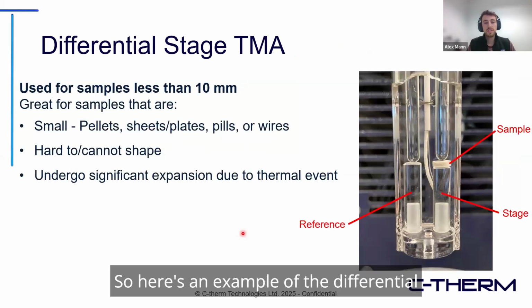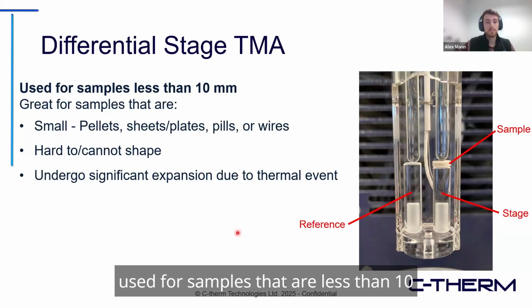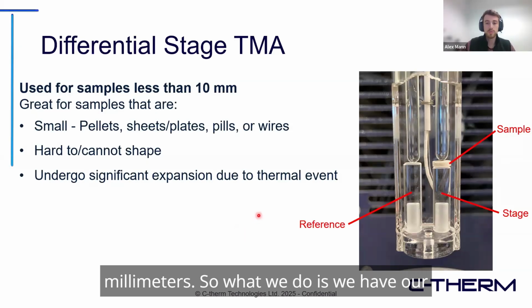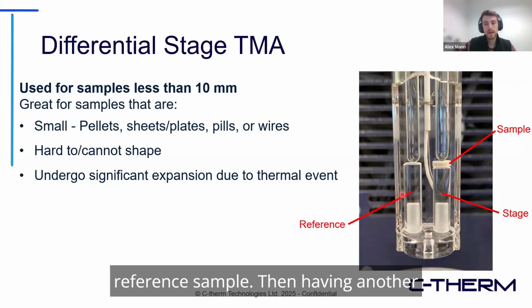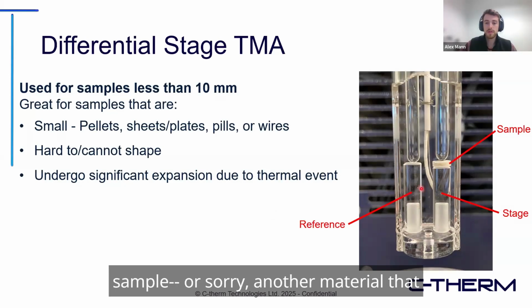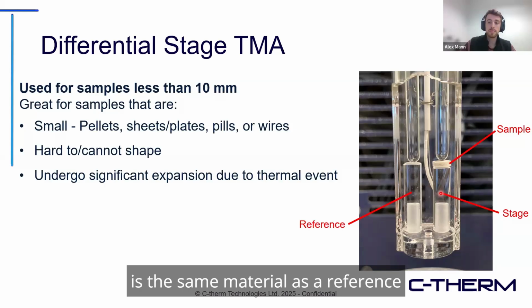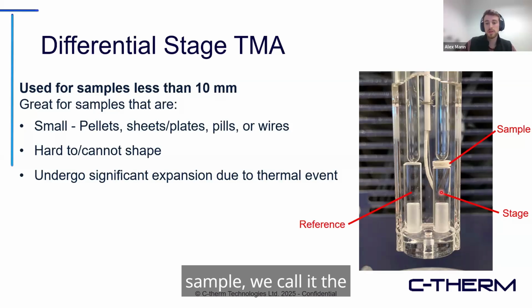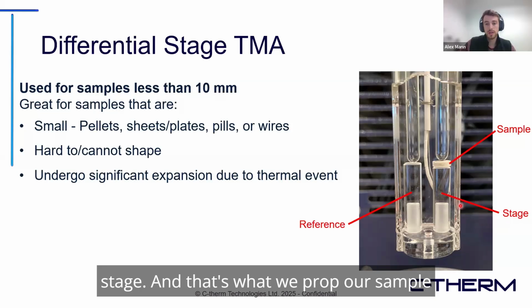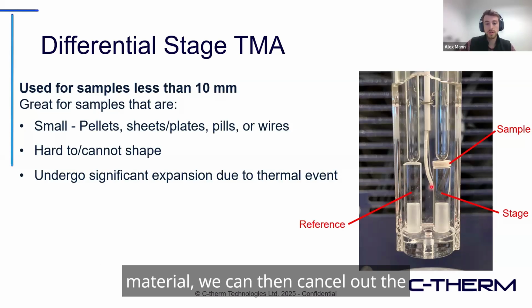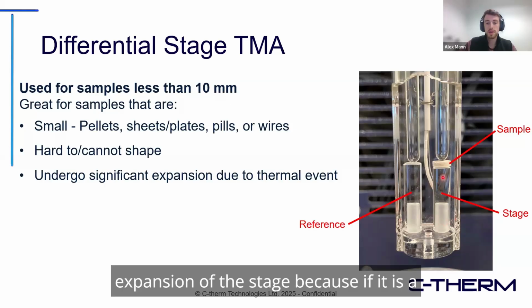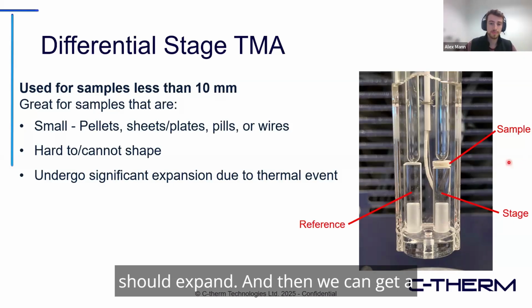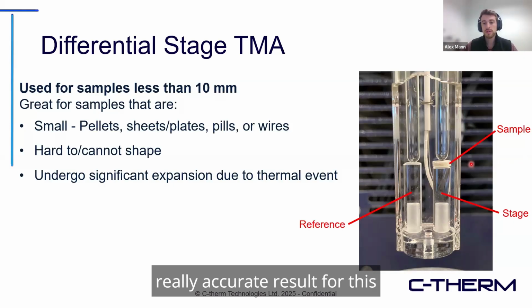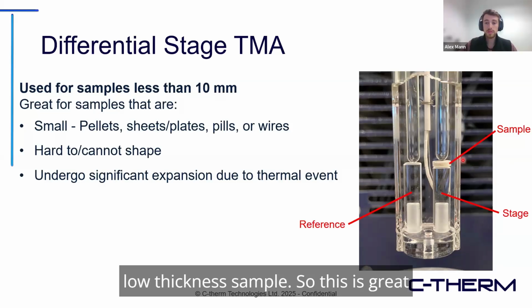So here's an example of the differential stage method that I just mentioned. It's used for samples that are less than 10 millimeters. So what we do is we have our reference sample, and then another material that is the same material as the reference sample, we call it the stage, and that's what we prop our sample on. Now, because these two are the same material, we can then cancel out the expansion of the stage because it is a reference material. We know how much it should expand. And then we can get a really accurate result for this low thickness sample.